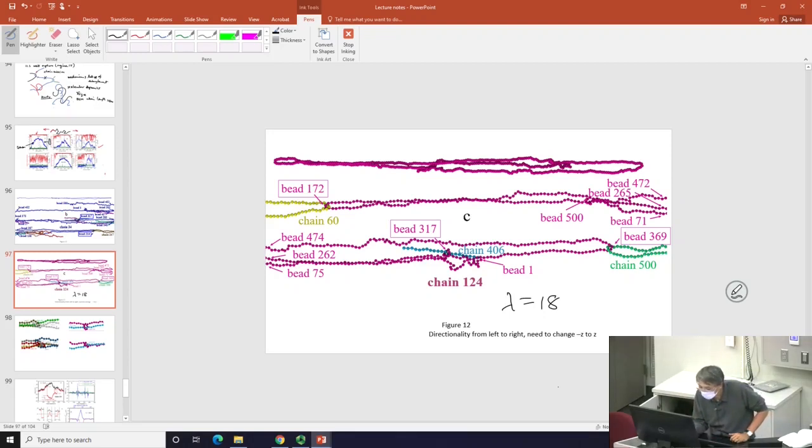You can see that this chain has 2 places of hairpins formed by the presence of the other chain. See, that's one here, that's the other one there. These are straightforward. To form this kind of junctions is obviously expected because of uncrossability, and chains are sufficiently long. What is mysterious is why the chain doesn't slide around the junctions.